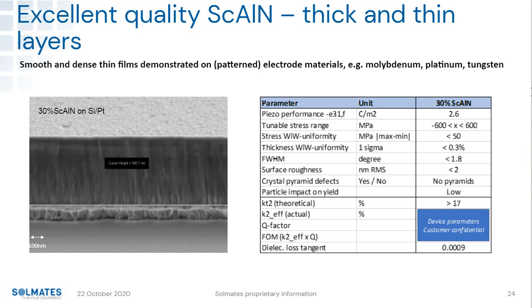So, like I said, theoretical value, we can do a coupling factor of 17. We know more about it, but cannot share. The bottom one, the dielectric loss tangent, it's typically not a parameter high on the list for the RF people, but it's been measured by several parties, and it seems that the dielectric loss, even for 30% scandium, because the losses tend to go up with scandium doping, it's really low. It's fundamentally lower compared to references from the PVD world. And it indicates our earlier claim.